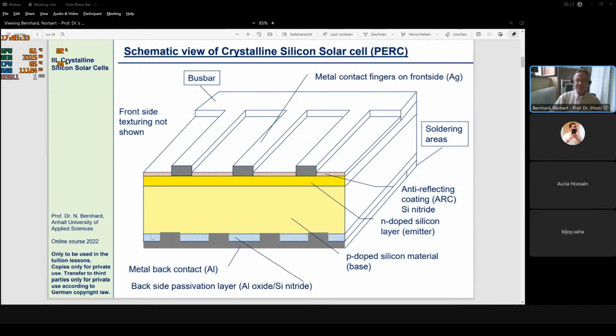The whole-area aluminum layer is replaced by another dielectric, which is an aluminum oxide and silicon nitride double layer. So this blue hatched area on the backside is this double layer. The double layer is not highlighted here, but it is a double layer. And this dielectric is interrupted at certain points, and this is not to scale. The area where the dielectric really covers the backside of the cell is much more than the contact area of the aluminum back contact. And the reason for this is, as I explained already, the dielectric passivates the backside much better than the aluminum does. The aluminum basically does not passivate at all.